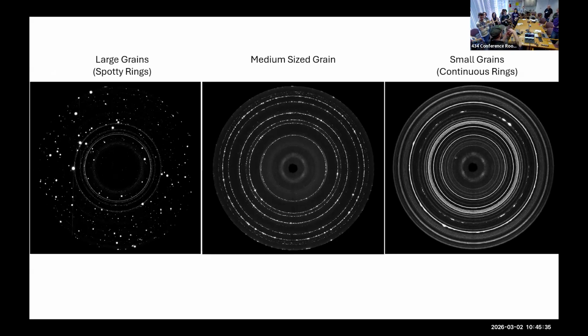So you have to have small enough grains that you can fit them into the diffraction volume, or fit them into the synchrotron beam, so that you can fill up this whole circle. Because the type of analysis, which we'll talk about a lot over the next 2 days, you need to have this circle filled up, or at least reasonably filled up. This one would be pretty hard to do. This one would probably be fine. And then here we just have smaller grains and we have perfectly filled in full circles.